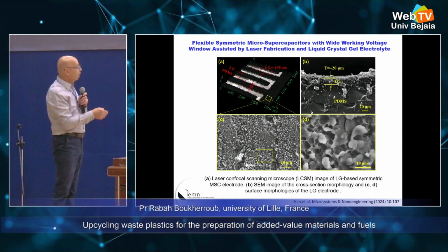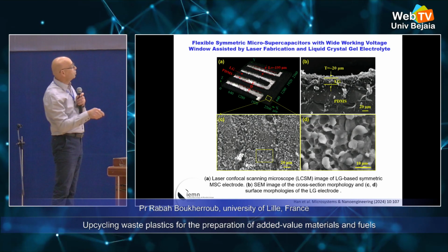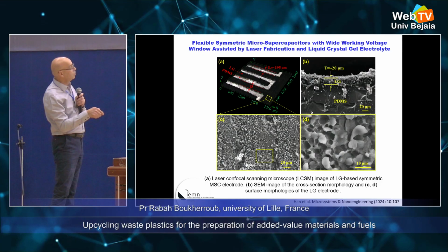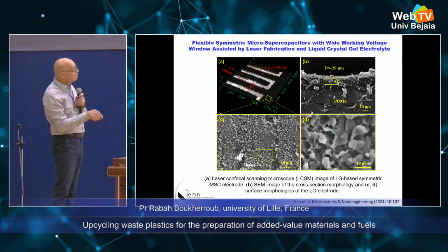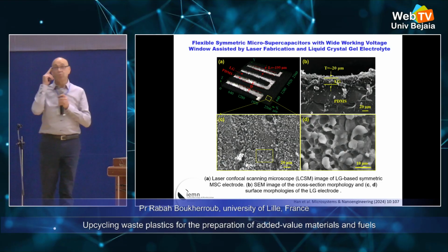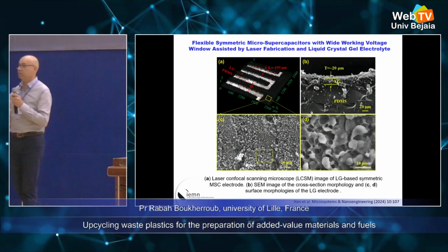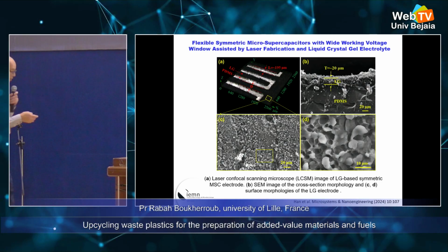Here are just some SEM images showing the thickness of this transferred laser-induced graphene with a porous structure. It's important to have a porous structure because then you have a high surface area, and you can indeed have much higher available surface to store the charges.